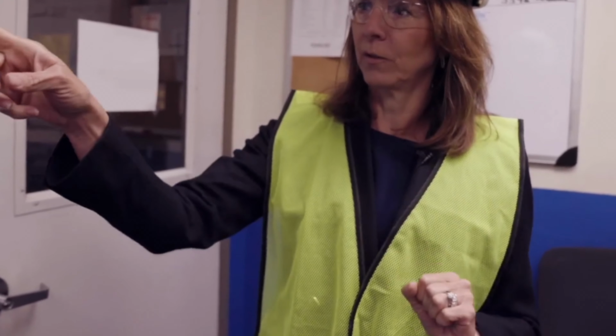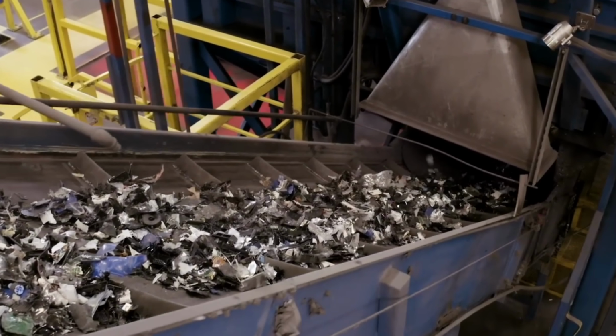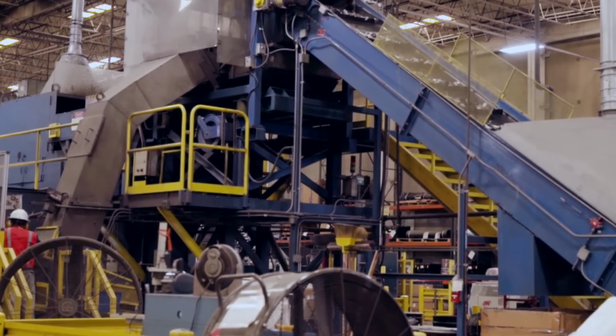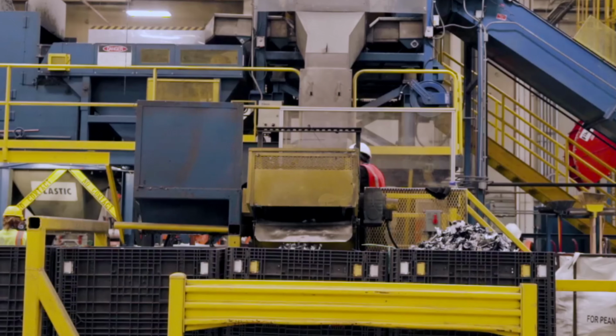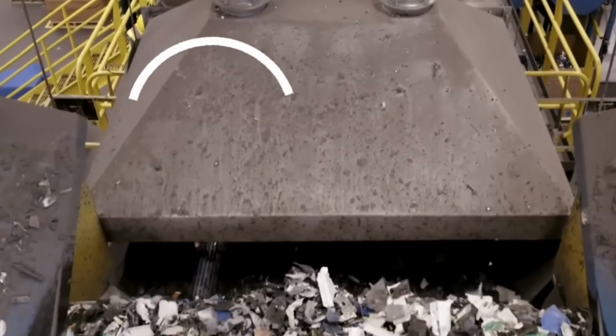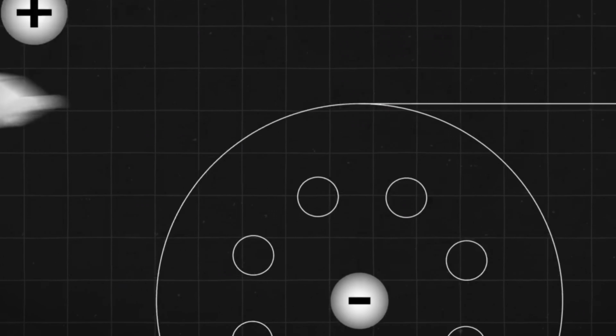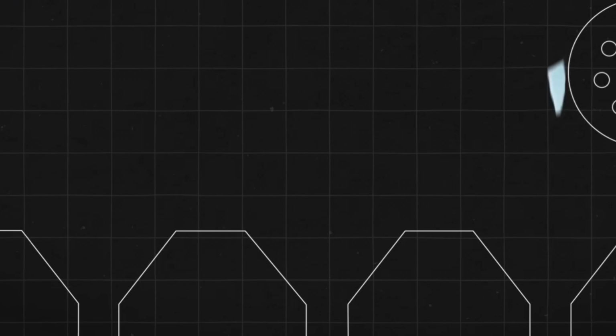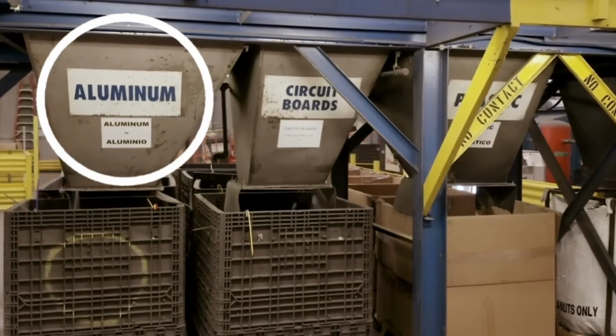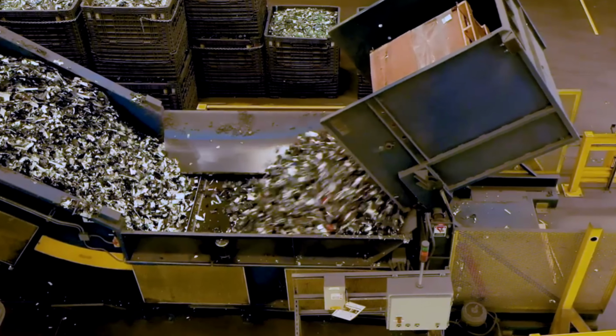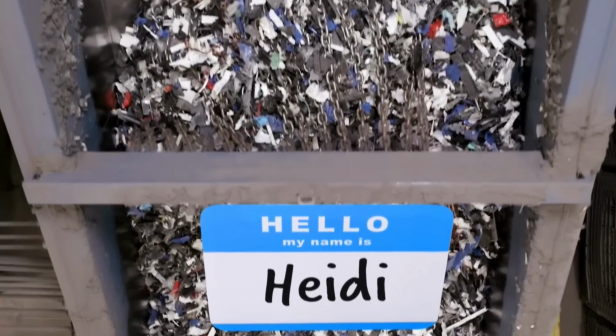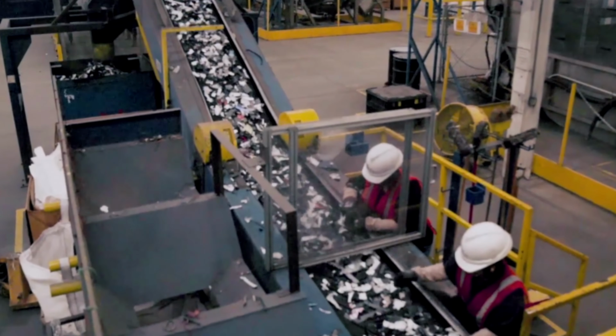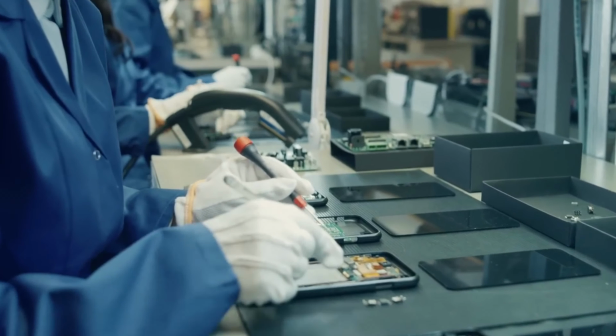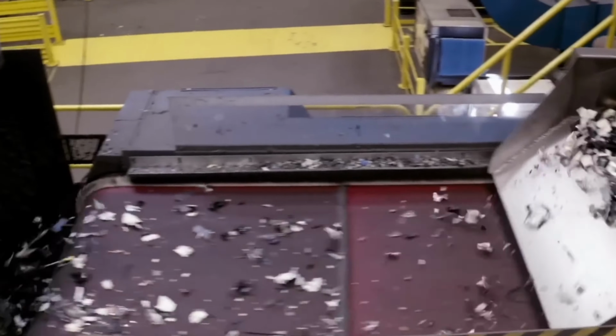Base metal recovery follows parallel processing streams designed specifically for copper, aluminum, and other common electronic metals that represent significant value despite lower per-pound prices compared to precious metals. Copper recovery uses specialized leaching chemistry that dissolves copper compounds while preserving other metals for separate processing streams, achieving copper purities suitable for direct reuse in new electronic products. Rare earth element recovery presents unique challenges because these specialized metals exist in very small concentrations but have extremely high values for advanced electronic applications. Rare earth processing uses complex chemical separation techniques that can isolate individual elements like neodymium, europium, and terbium from mixed rare earth concentrates, often requiring dozens of processing steps to achieve final product specifications.